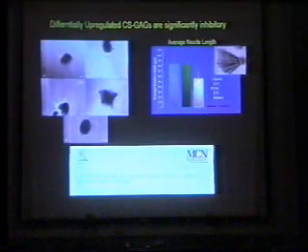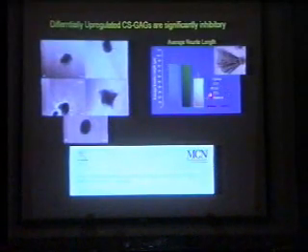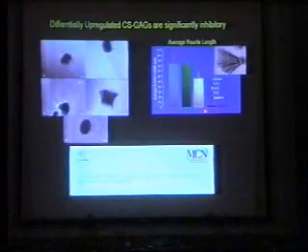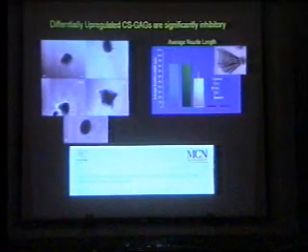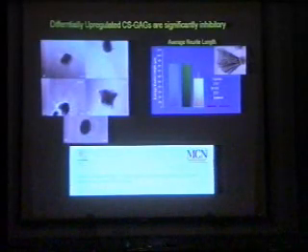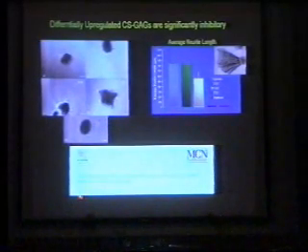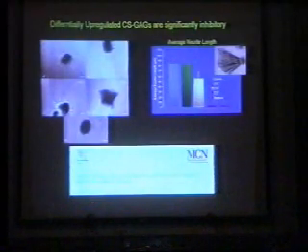CS-E, which is 4,6, is also inhibitory but not as inhibitory. We do not see any inhibition from the 6-sulfate. So CS4 is present a lot in the normal brain, but 4,6 is potently inhibitory, as inhibitory as the entire molecule. Okay. And nobody really had shown this. Ours was the first lab to demonstrate that even 4,6 existed in scar tissue. Nobody had even looked for it. So we were happy to report this in the last year.